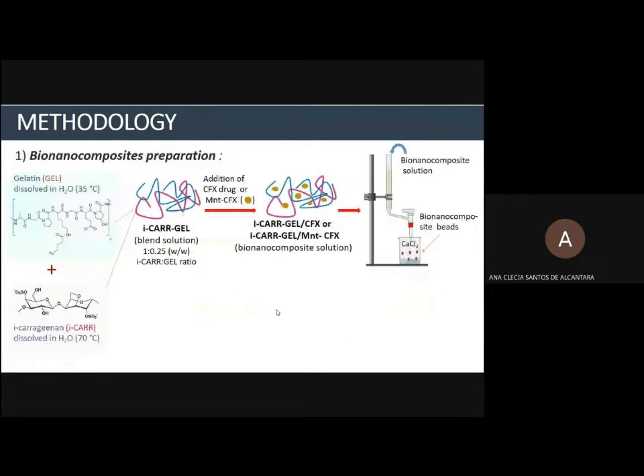For the bionanocomposite preparation, a mixture of gelatin and iota carrageenan dissolved in hot water is prepared, obtaining in this case a blend solution. To this blend solution is added the ciprofloxacin drug, in the free form or previously intercalated in montmorillonite, in the same amount of ciprofloxacin, approximately 0.1 gram, obtaining in this case the bionanocomposite solution.